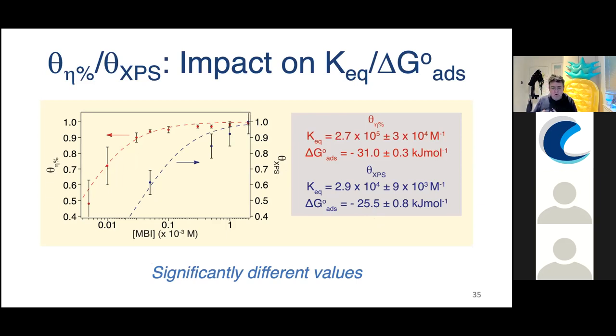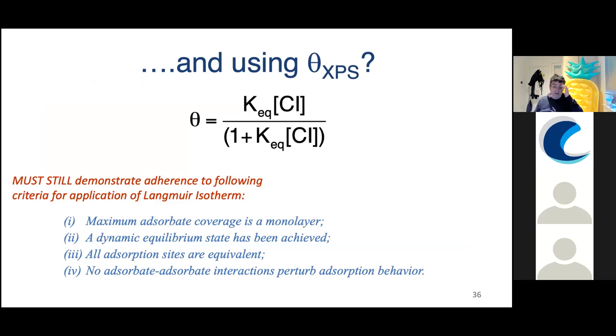The key question: can we use theta XPS instead? Should we be using that? And maybe we can. However, there are concerns even about that, and whether that number we've got out, minus 25.5, is reliable. I'll just explain why. If you look at this equation, this is a Langmuir isotherm. But if you use this equation, you have to demonstrate adherence to the following criteria so you can apply it. The maximum adsorbate coverage needs to be 1, so monolayer. Dynamic equilibrium has to be achieved, so we don't know the first one exactly. As regards dynamic equilibrium, actually in corrosion, is never strictly a dynamic equilibrium. There's at best a steady state condition. Whether that is okay is a matter of debate.